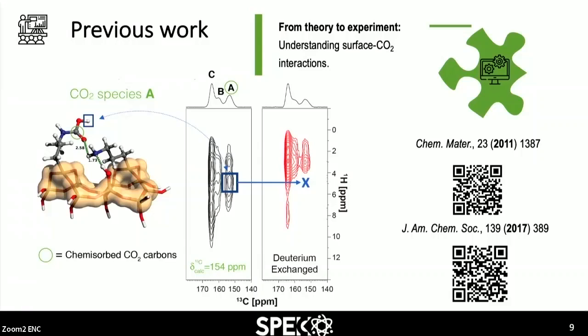And this paper from 2011 was actually the first experimental evidence of the carbamic acid moiety in solid adsorbents. And this way, we were able to give an atomic level insight into the CO2 speciation of chemisorbed species formed at the surface of silicas.